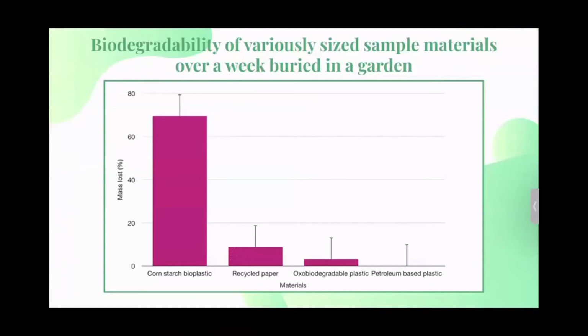As a result, from the biodegradability tests, my original hypothesis of the cornstarch-based bioplastic having the highest percent mass loss held true. The biodegradability of regular cornstarch-based bioplastics is high in general, being able to biodegrade within days. This held true with my research, as the cornstarch-based bioplastic had 69.43% mass loss. Following that was recycled paper with 8.82% mass loss, the oxo biodegradable plastic with 3.19%, and the petroleum-based plastic with 0.014%.